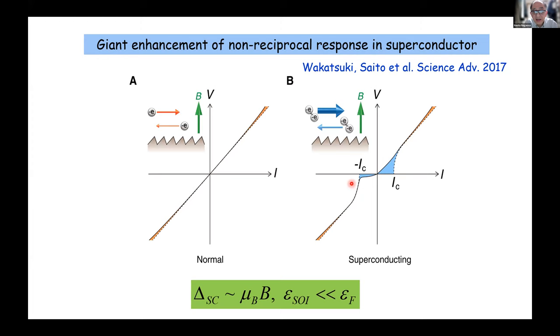And then this IV characteristic is slightly above the transition temperature. So then your resistivity is highly asymmetric between the positive and negative direction. So this means that once the Cooper pair tends to form, the conductivity or current due to this superconducting fluctuation shows a rather large asymmetry between the positive and negative directions. So the basic reason is the following.